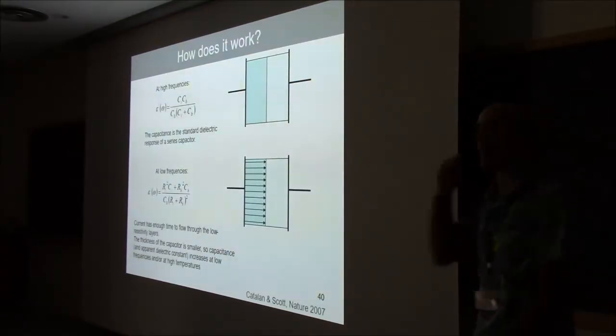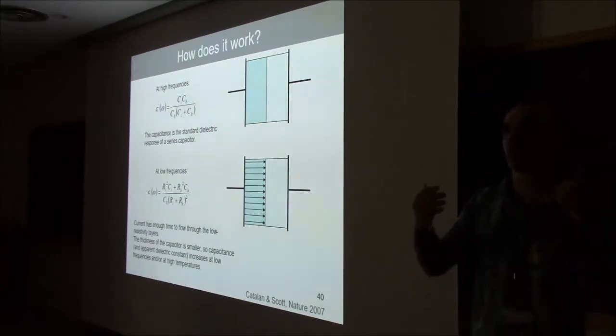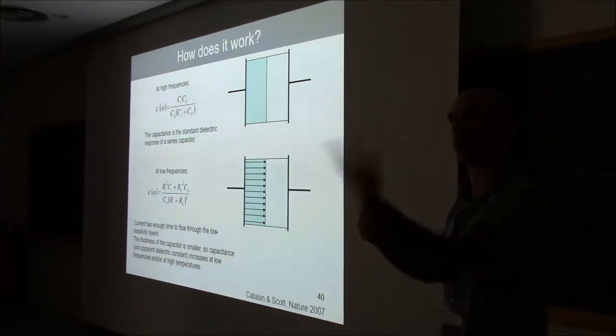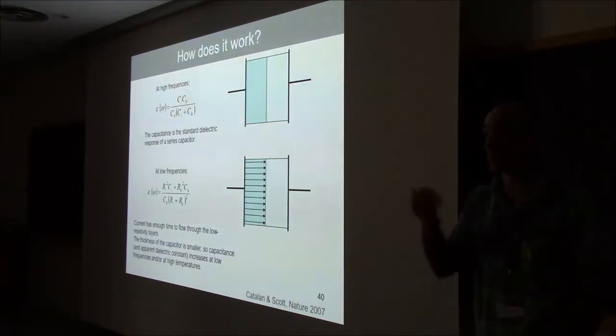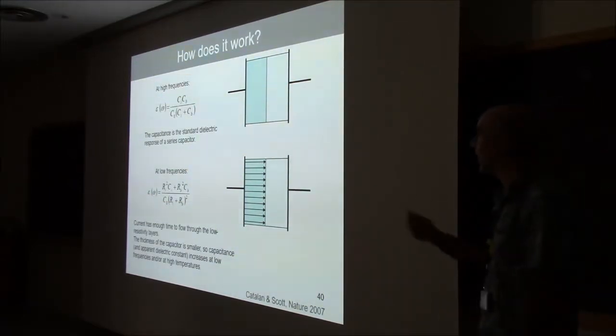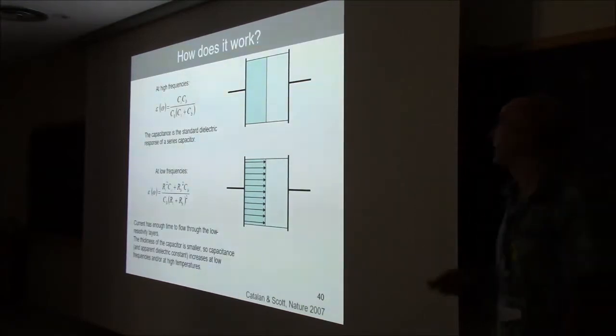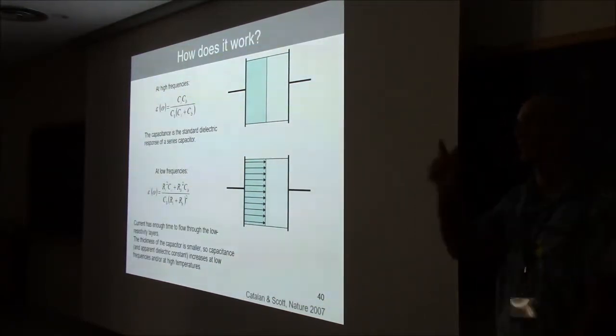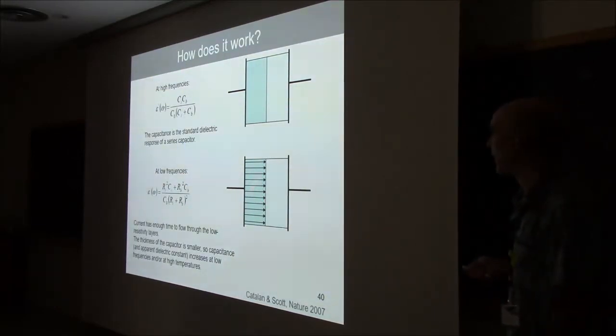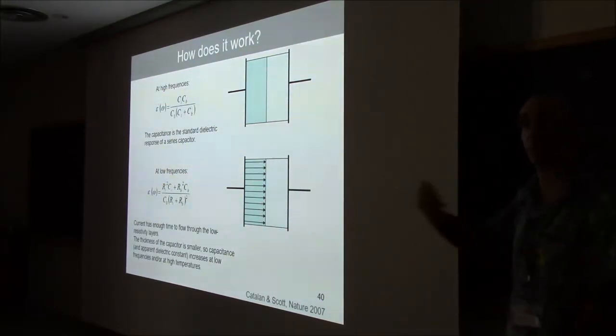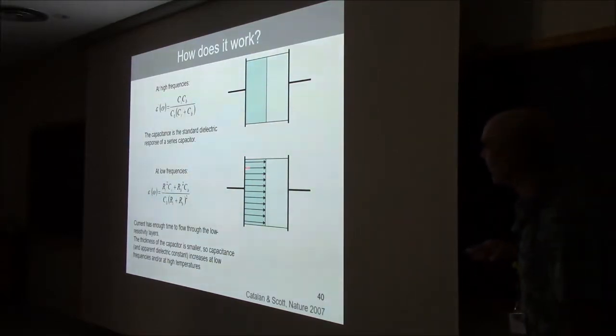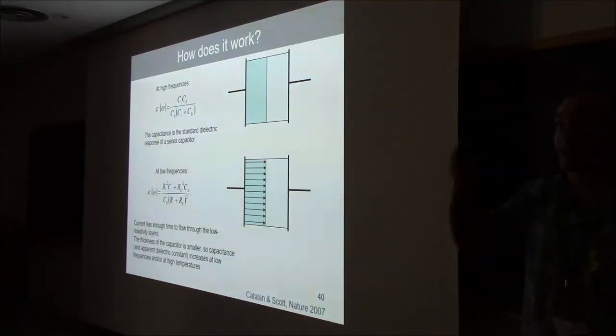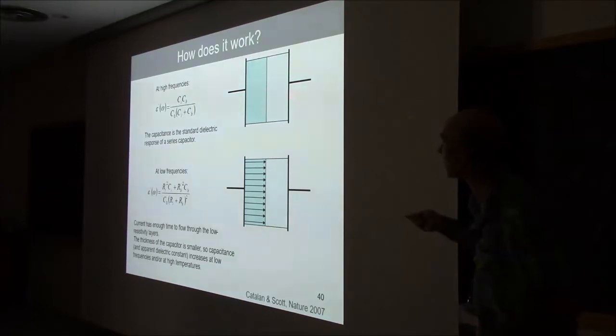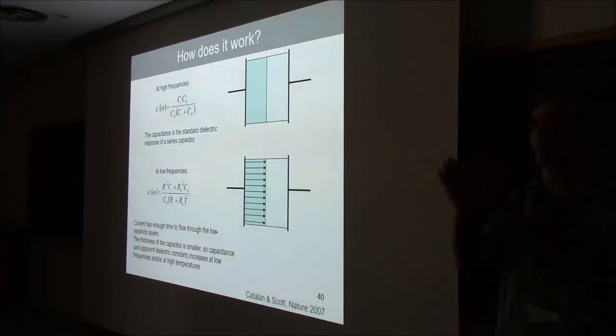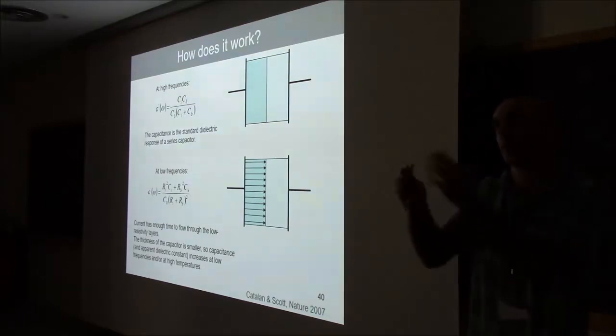If you measure at super high frequency, high enough that the leakage current does not have time to travel across your semiconductor, then the dielectric response that you're going to measure is a true dielectric response. If you measure at a lower frequency, however, it might happen that one of the two components in your circuit allows the current to travel across it because it's leaky, right? And in that way, what you have is basically like an extension of the electrode. The new electrode is no longer here, it's here. Your dielectric component is no longer the entire thickness of the capacitor, it's only the thickness of the element that is insulating, or that is more insulating.